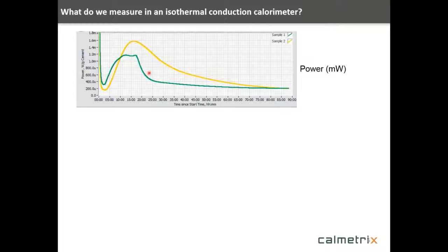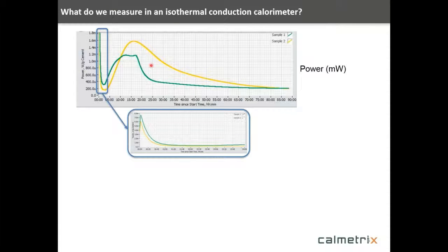This happens to be two different cement samples, and you can see some pretty drastic differences between these two samples. If I blow up just this part of the curve, there are a couple things going on. Of course, as you know, as soon as you add water to the cement or concrete, the reaction takes place almost immediately. So typically we do that outside of the calorimeter and then put the sample into the calorimeter. So that reaction is taking place almost instantaneously.